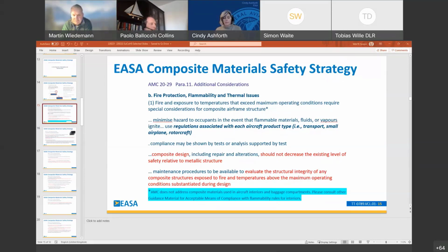So in the general aviation world, we used to have a factor of 1.15 due to this variability we had to account for whenever we use hand layup. Or in this world here, primary structure, commercial structures, we have, for example, a knockdown whenever you work with metal and use casting, you have an extra value. So in this case, I can see where the advantage is from a regulatory point of view when we work with robotic layup, when we ensure consistency against a type of composite manufacturing that has a larger scatter.